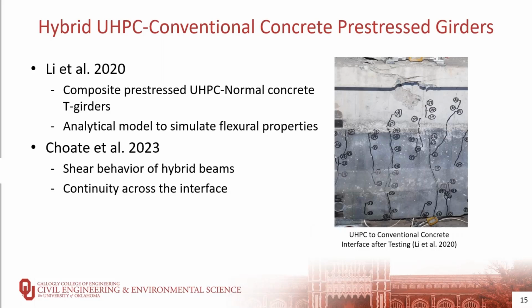As full UHPC prestressed girders might be more expensive than conventional concrete, a few researchers studied the hybrid option, where basically UHPC and normal concrete were used together. Li examined the flexural properties of composite prestressed UHPC normal concrete T-girders. The UHPC was placed in the tension region and the normal concrete in the compression region, as shown here in the figure on the right. They tested 10 large-scale composite prestressed girders and 1 normal concrete prestressed girder, along with an analytical model to simulate the flexural properties of those composite girders.